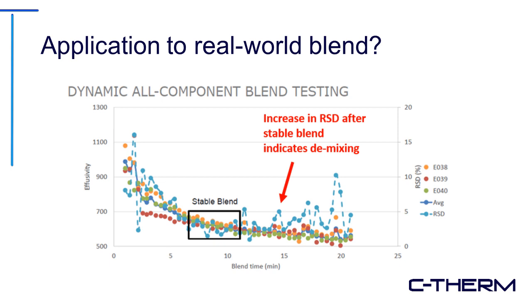So how does this work in a real-world situation? This is a very quick example. We covered a bunch of other permutations of things that could cause it, including looking at spotting additives as they're added into a blend, those sorts of things. But this is just one plot from the paper that we wrote. You can see here we've got 4 different components, and we can identify, using the thermal effusivity, a region where the blend is stable, and then a region where the relative standard deviation starts getting spiky, and it spikes up in some cases above 10% relative standard deviation. Whereas in the stable blend region, it's typically less than about 3.5% in most cases.